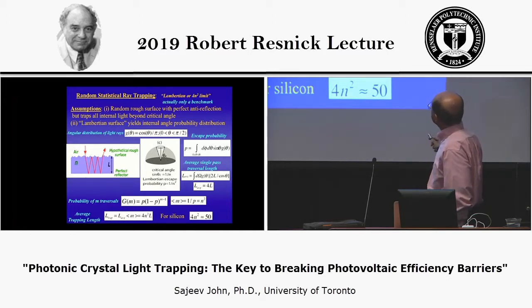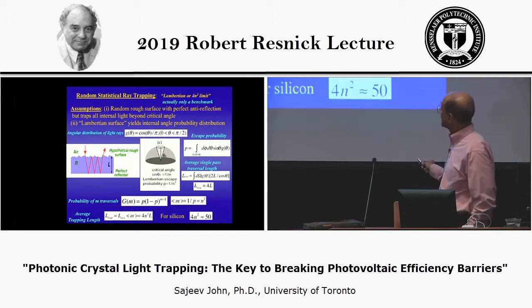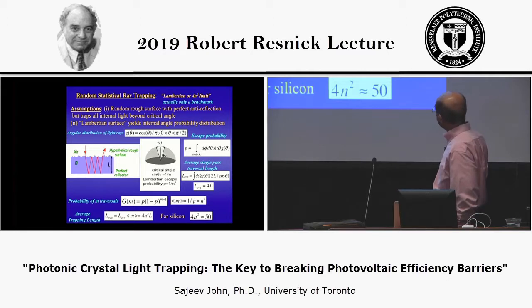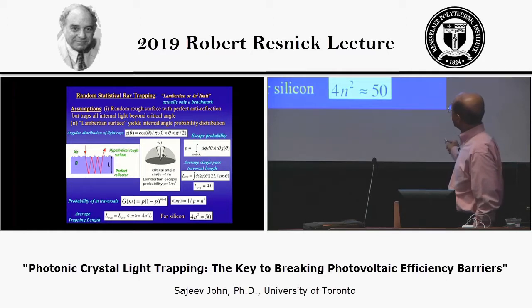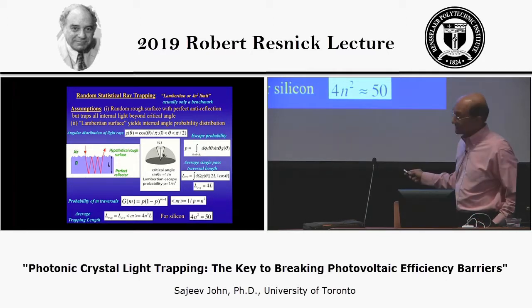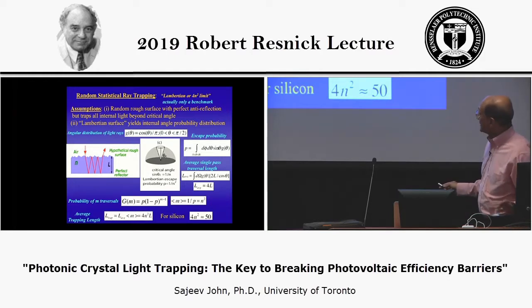And if I weight this set of rays with respect to this distribution function and then integrate from 0 up to the critical angle, such that the sine of the angle is 1 over n, I find that the escape probability is given by 1 over the square of the refractive index on a single bounce. And then you can ask, what is the average path length due to one bounce? It's 2L, the thickness of the cell, divided by the cosine of angle theta, multiplied by this distribution function. And then the average path length of a single bounce is actually 4 times the physical thickness of the cell.